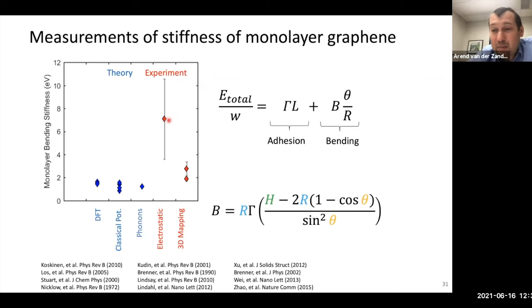They were not getting the same numbers, and the numbers were all over the place. So when we measured it using our technique, the steps, what we got were very tiny values that actually matched very nicely to the predictions. And so we were actually able to directly measure the bending stiffness of this graphene and have it meet with predictions.